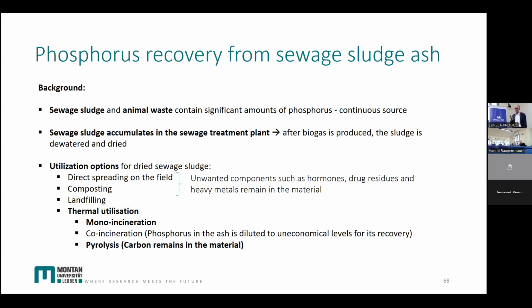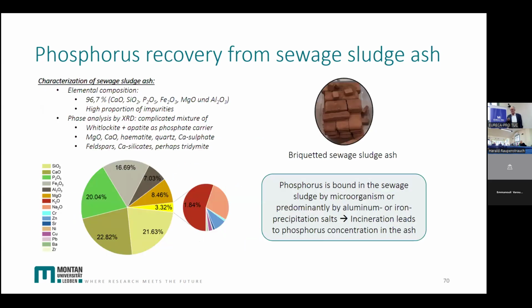Or you could pyrolyze it, and then you have carbon and phosphorus. So just to get an idea how much phosphorus is in the sewage sludge ash, it varies. It's completely different. It's a question where this sewage sludge ash comes from. But you see about 20% P2O5 is in this ash, which is quite a lot. But you also see you have an iron oxide content of nearly 17%. This iron oxide comes from the sewage sludge plant. And this can cause problems because the phosphorus tends to react very rapidly with the iron and creates iron phosphate.